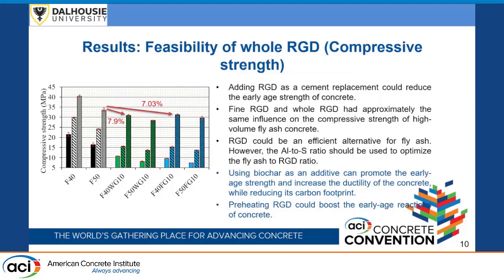However, we do that in the mortars, not in the concrete, so the data are not here. And when we use artificial intelligence, we find that the Al to S ratio in the fly ash and RGD could be used to optimize the dosage of recycled gypsum drywall.